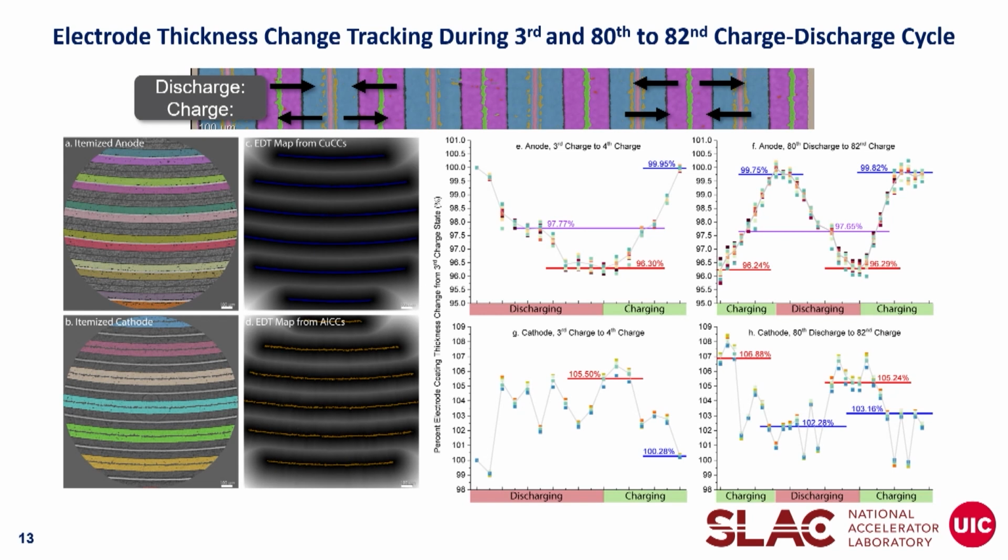We have different staging compounds, which are defined by the amount of lithium that goes in the structure. And you will see this plateau in expansion upon discharge and charge, though we have a higher rate of charge here, so it's not as resolved. The cathode structure is a lot more noisy data, but we generally see the expansion contraction and the reverse relationship as we would expect in the charge-discharge process.